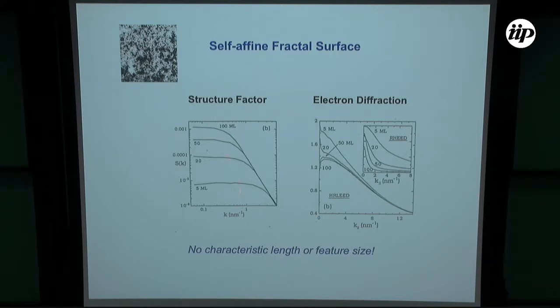is that neither of these functions, or any other quantity that you like that you measure, is a measure of the morphology. There's no characteristic length. This is k, so it's related. The wave vector is related to the wavelength of observation, and there is no characteristic length. There's always some kind of a decay which is related to the surface fractal roughness of the surface, which you might be familiar with. So these surfaces are basically self-affine fractals, and the slope of these things is that exponent alpha, and this was very well defined.